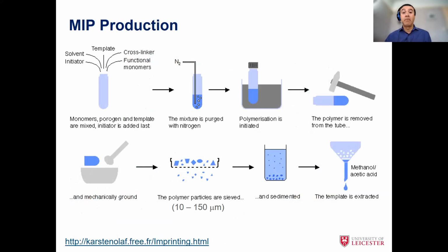If you wanted to go in the lab and make and synthesize them, this is a rudimentary, rough and ready method where not necessarily a specialist scientist needs to come into the lab. Essentially you have your solvent, you add an initiator for polymerization, you add your template, you add your monomeric mixture, you put it in the test tube, and you bubble nitrogen gas to purge any oxygen that can scavenge the reaction.